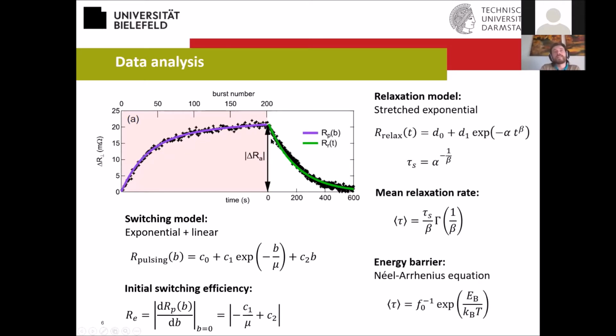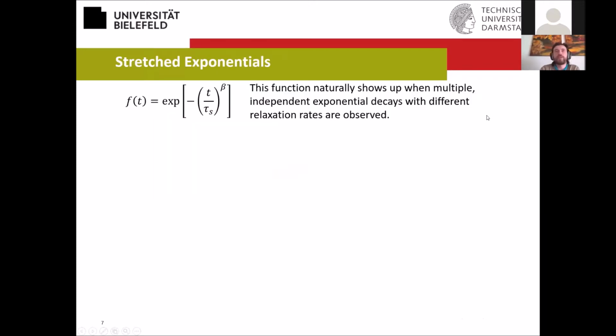Then for the relaxation, we apply stretched exponentials, which have this form. So we have a constant plus an exponential where the time variable has an additional exponent. And from this, we can obtain a so-called stretched relaxation time from these parameters alpha and beta. And then we can calculate a mean relaxation rate, which is calculated with this expression, including the gamma function. And then having this parameter, we can calculate the energy barrier that basically leads to this relaxation behavior from the Néel-Arrhenius equation. Okay, now you can ask yourself, why do we use these stretched exponentials?